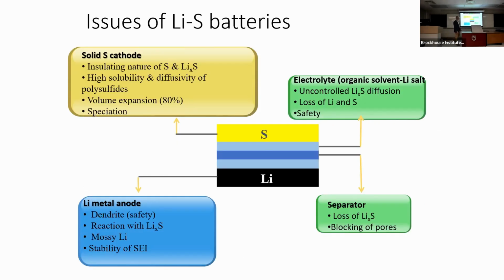Don't quite get the blocking before that. I think there is a separator in between, and let's say it's a macroporous material through which all the lithium-ion conductivity must pass. But if polysulfides are formed and they block the pores, the lithium ion cannot move through it.